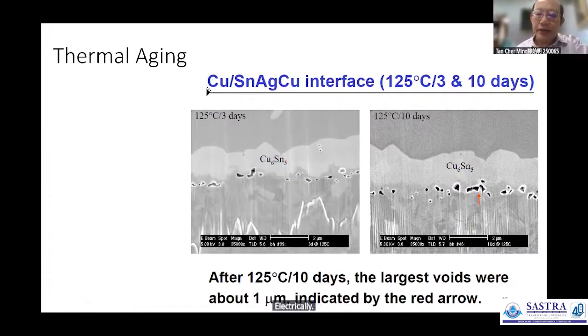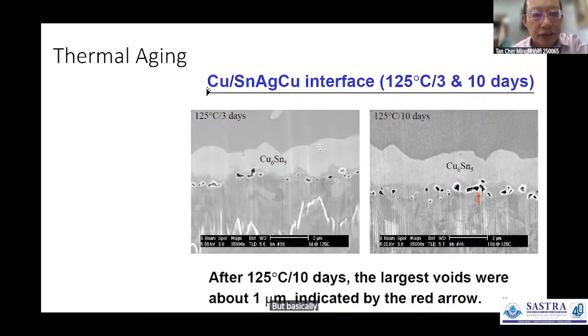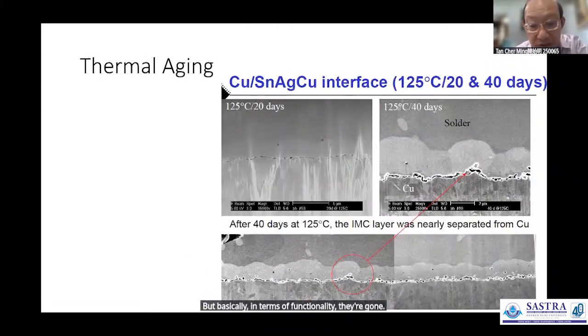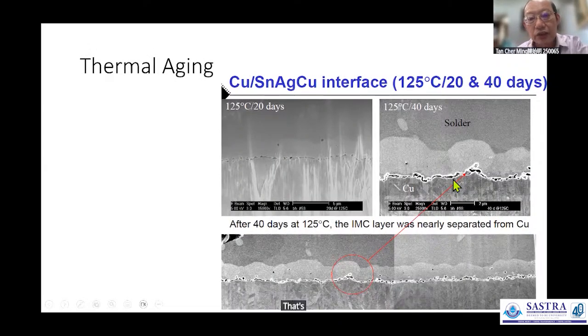But mechanically, because they're still inside the package, you don't see them falling apart. But basically, in terms of functionality, they're gone. You can see that they're forming a line. That's why in 125 degrees C, 40 days, the one drop, everything is gone. This is what you can see.